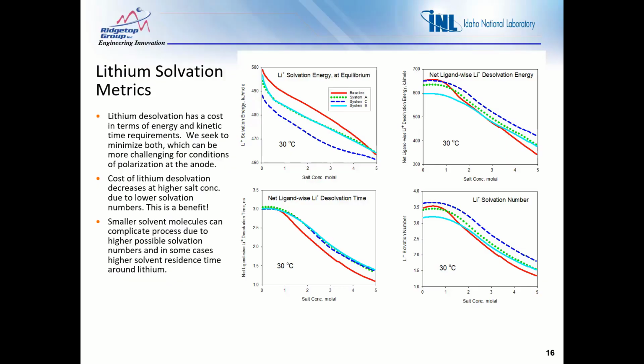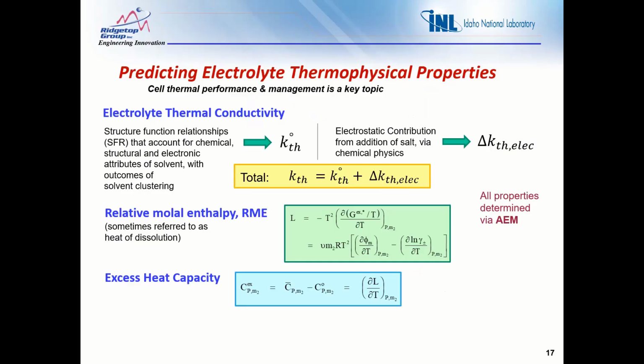Okay, next slide. AEM also produces a suite of thermophysical properties. I've shown here just a very high level view of these 3 properties. Electrolyte thermal conductivity: we use structure function relationships to derive the pure solvent and solvent mixed thermal conductivities. And then we add an electrostatic contribution from the addition of salt, and that's driven by chemical physics formula that are tuned into the attributes of the solvated lithium and counter ion, or whatever the salt might be. It doesn't have to be lithium based.